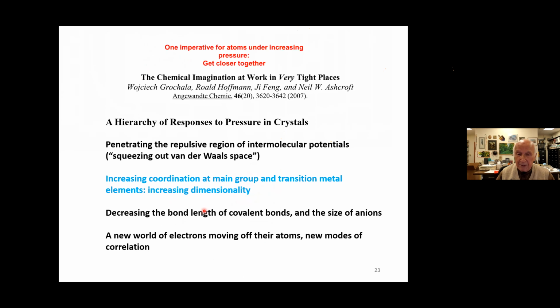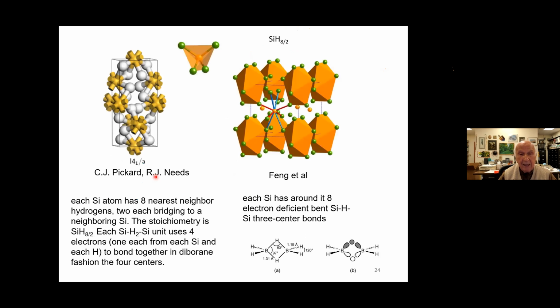The next thing that happens as you squeeze is you must get closer together. Let's imagine the 2 molecules squeezing. They're coming closer together. At some point, things that are attached to one molecule are getting close to the nucleus of the other molecule. And what you get is an increase of coordination. At main group and transition elements, you get an increasing dimensionality. Let me show it to you for silane again. Silane initially is a molecular crystal of SiH4 molecules like methane.